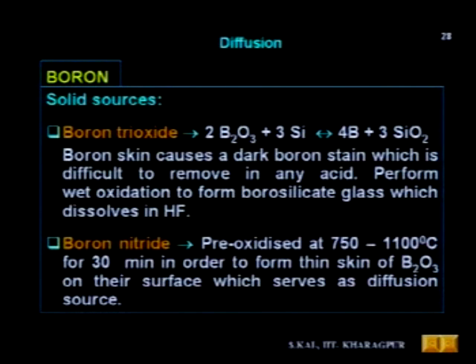So in order to prevent that, it is better to use boron nitride, which is not so easily damaged by H2O molecules, and you can always keep it at a higher temperature, preserved at about 250 degrees centigrade. Whenever you need it, you take it from that source which is kept at 250 centigrade, then you activate it and use it as a source material. So that's why boron nitride is popular compared to boron trioxide.